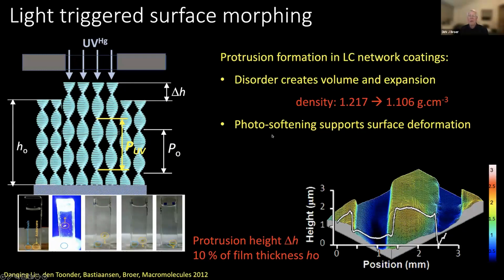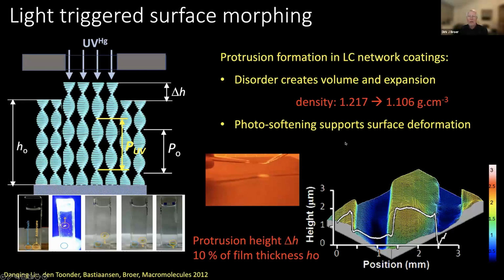Another effect that takes place at the same time is so-called photo softening. In this case, because of the presence of the azobenzene, the system undergoes a transition from glassy-like to more rubbery-like, and that basically enables the deformation of the surface. It is hard to imagine that if you have a glassy surface, you will get these high surface protrusions being formed.